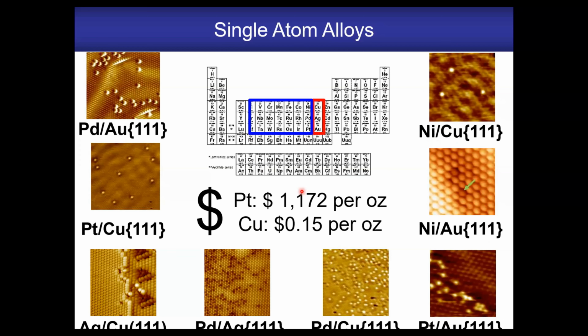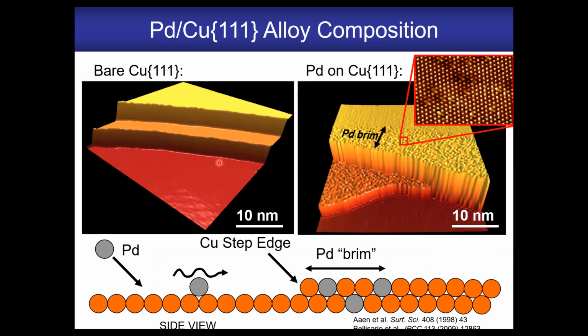So if you can do catalysis this way, you can obviously make a big cost saving if you have something like platinum alloyed in copper, because of their vastly different prices. And like I say, a lot of the experiments I'll show today are working at the 1 or 2% doping levels of the expensive reactive element. So we start with incredibly clean surfaces, and I'll talk today about copper. It's very important to have a clean surface because you don't want to be looking at the reactivity of minority defects in these surfaces. So we can clean these surfaces in ultra-high vacuum to better than 1 part in 10,000 atoms.